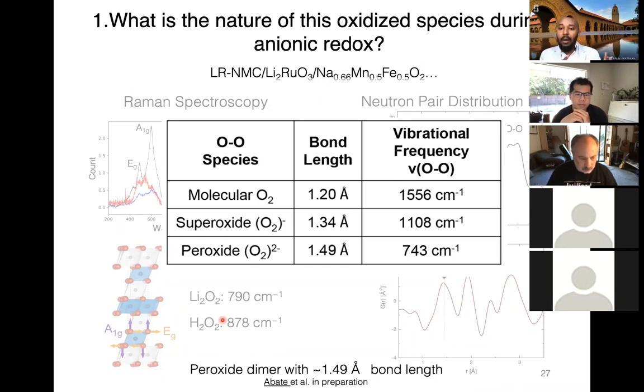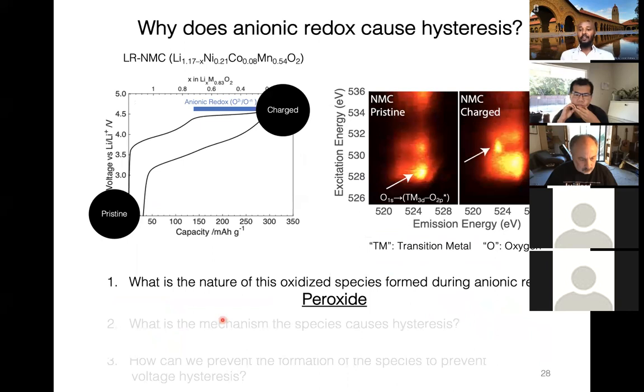And from using the Raman, the neutron PDF, and the RIXS simulation, it indicates that what we are forming is a peroxide dimer with a bond close to 1.5 angstrom bond length. But the most important thing here is actually the fact that we are forming a short covalent bond between two oxygen atoms. In this case, it happens to be the peroxide.